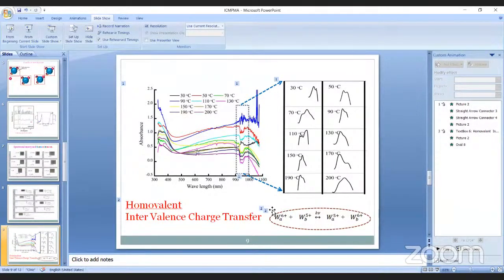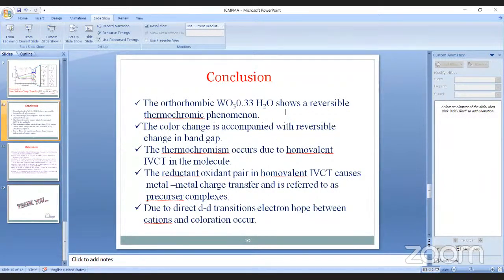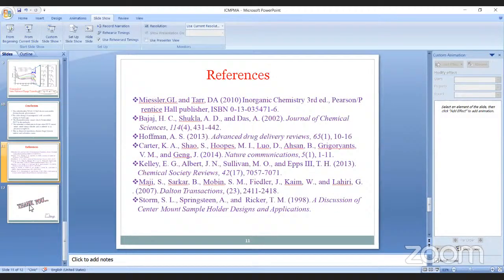In the early stages of the study, we identified that the material has multivalency and shows W6 plus and W5 plus, which is confirmed from EDAX and XPS measurements. This shows the swapping of oxidation state between these two states with the absorption of energy. The reductant-oxidant pair W6 plus and W5 plus taking part in the homovalent IVCT mechanism causes metal to metal charge transfer, which is referred to as precursor complexes. Due to direct d to d transition, electrons hop between these cations and the coloration occurs in this material. These are the conclusions obtained in the study and some of the references, and thank you.